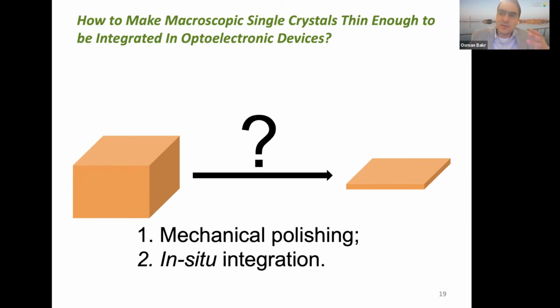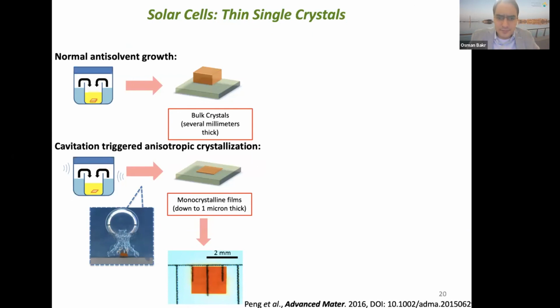With materials such as perovskites that have low formation energy, that are sensitive to many solvents, thin for device applications. And we started looking at how can we control the nucleation and growth. And one of the things we discovered serendipitously was we found that if you introduce a sonication pulse prior to solution supersaturating, you can create a cavitation bubble that spreads the crystal growth on the surface. And so instead of getting a bulk crystal that grows in thickness, you can get a very thin crystal that's a few thousand nanometers in thickness, but